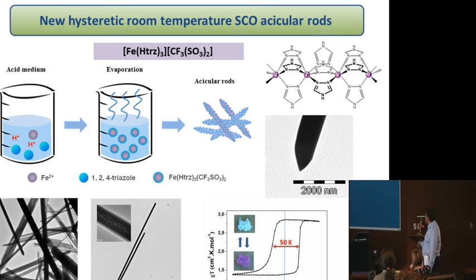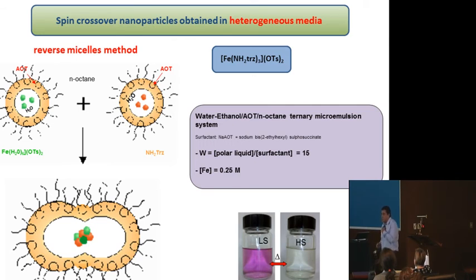This is a very nice result, because this new complex presents a spin crossover perfectly at room temperature with a large hysteresis. This is quite scarce in the field, and very useful for applications. Again, if you want to go towards small nanoparticles, the best way is to use reverse micelles. So we again use these techniques to elaborate nanoparticles of this family of complexes. Again, you can play with the concentration and with the ternary systems, and we obtain stable microemulsions containing small nanoparticles of this complex.